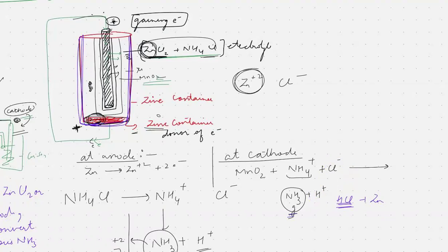So I did this one experiment. I bought a new cell and I left it in the sun for over a month. What I found was that the cell started leaking. I pulled off the label of the cell, and the silvery, shiny metal was no longer silvery, it had become a little corroded, because HCl started coming out of the cell and reacting with the zinc jacket.